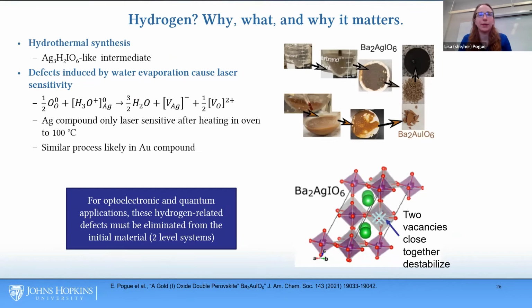I was able to track the likely kinetics of this reaction, and was able to come up with some defects that I believe are responsible for both the water stuck in the structure and also the apparent instability of this material only after it's been dried